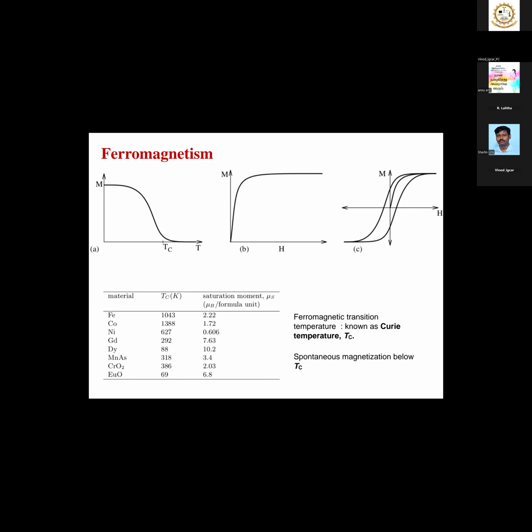Here, the main difference is that spontaneous magnetization means this magnetization is generated even without applying an external field. Generally, for paramagnetism and diamagnetism, you have to apply an external field H, then the system will generate its magnetization or moment. That is the response you will get. But in ferromagnetism, even without an externally applied field, in the ferromagnetic state the material can show spontaneous magnetization. And second is the initial magnetization curve. And the last figure, C, is the full magnetization, which is hysteretic. Magnetic hysteresis will be there.